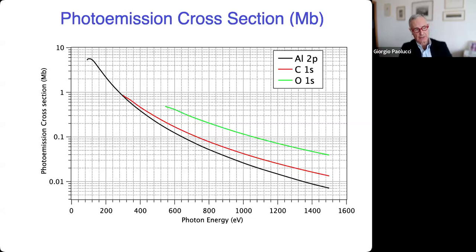So the onset of photoemission is, of course, the energy of the core level you're looking at. And depending on the energy, you see that the absorption is favored or non-favored. And as I said, all of them decrease with photon energy. And you see they decrease a lot, because if you look, for example, at the aluminum 2p, you get 2 orders of magnitude if you move from, say, 200 to 1400 electron volts. So it decreases a lot. And I'm going to try to explain to you why this happens.